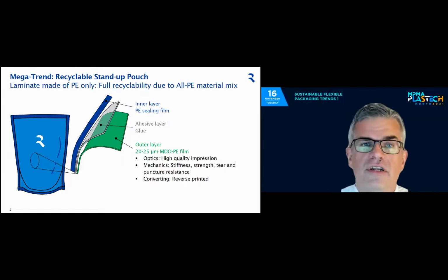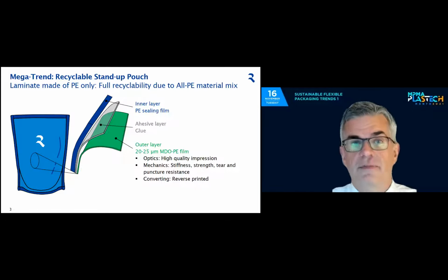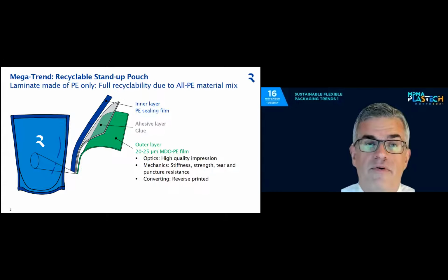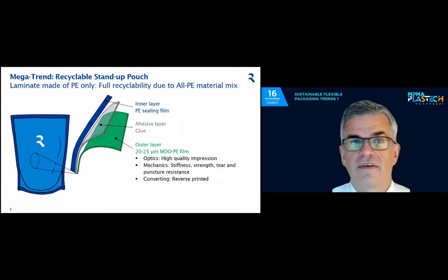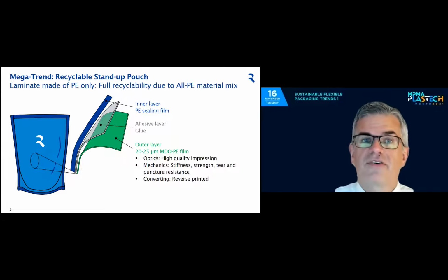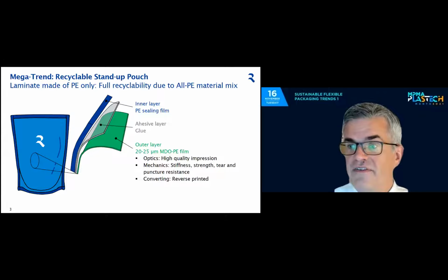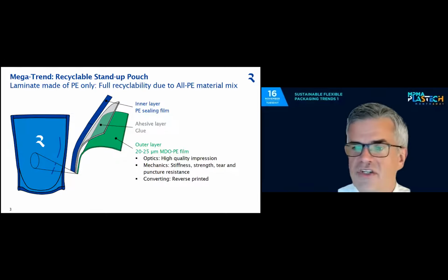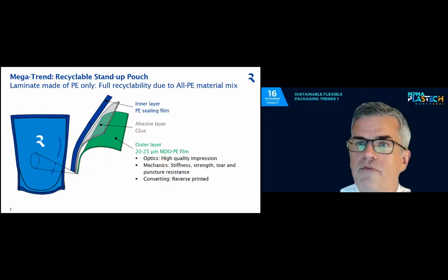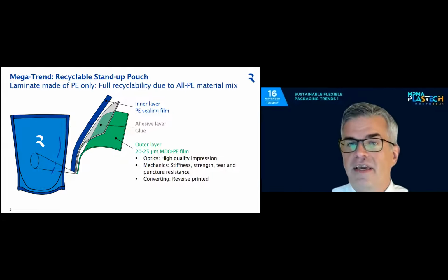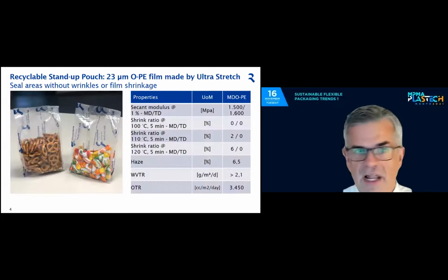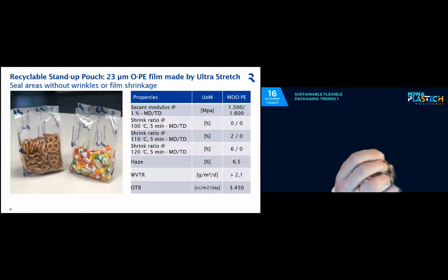And well, one solution is the stretching of PE film with a certain content of HDPE, because if I stretch it like 400, 500, even 600% is not uncommon from primary thickness, say 130, 120 microns, down in a range of 20 to 25 microns, the nature of the film is changing. I get very good optic properties. I improve the stiffness, the strength of the film, and I get a quite stiff film, which is convertible either by flexo or by rotogravure printing. So by doing so, I get a film which I can use for the PET replacement, and I can create a fully recyclable stand-up pouch like this one, which I hope you can see a little bit at least,